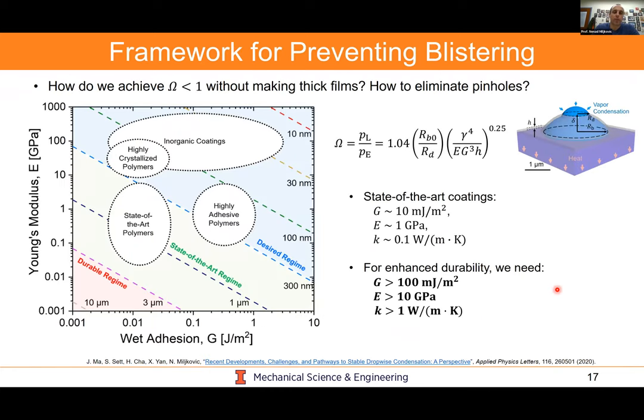And so what this enables us to do now is create a regime map based on this omega and actually plot where we wanna be in terms of the coating's Young's modulus and what we term as the wet adhesion, which is this G. It's basically the coating adhesion to the substrate. And so you could see here that where we want to be, which is basically these dotted lines for a particular thickness, is where the regime is durable. This is kind of where we are in terms of the state-of-the-art polymers. We have fairly low Young's modulus, fairly low wet adhesion. Inorganic coatings have very high Young's modulus, but they have fairly poor wet adhesion. So ideally where we want to be is actually for very thin coatings. We want to be up here in terms of our wet adhesion and Young's modulus, for example, for whatever coating we develop. So for state-of-the-art coatings, we're talking about a wet adhesion of 10 millijoules per meter squared, Young's modulus of 1 gigapascal, and a thermal conductivity typically of 0.1 watt per meter Kelvin. Really where we want to be is an order of magnitude higher for every one of these parameters for whatever coating we develop.